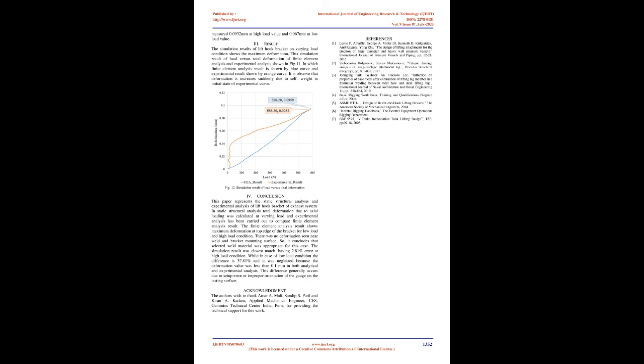The simulation result was closest match, having 2.81% error at high load condition. While in case of low load condition the difference is 37.81%, and it was neglected because the deformation value was less than 0.1 mm in both analytical and experimental analysis. This difference generally occurs due to setup error or improper orientation of the gauge on the testing surface.